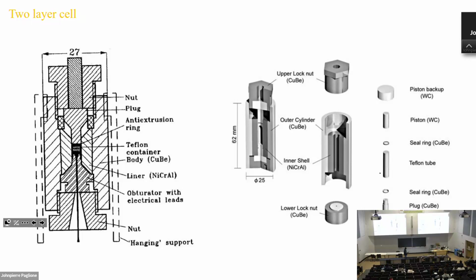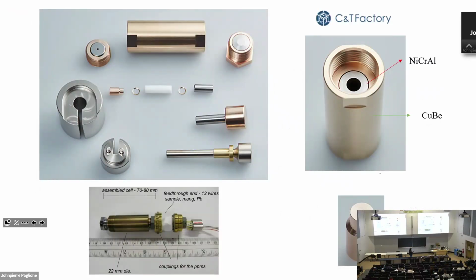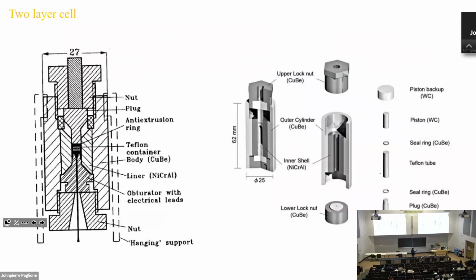Okay. This is the type of cell that we use. It doesn't have that mushroom seal, but it works pretty well. It's from this company, and you can see the cell. We have two layers. The outside is beryllium copper. Inside, the color is different. It's this nickel chromium aluminum. And then you have this. Here's your piston. That's tungsten carbide. Then this is that anti-extrusion ring, and this is your Teflon tube for the sample space. And here's your feed-through. And this is the bottom one. There's a hole the wire can go through.